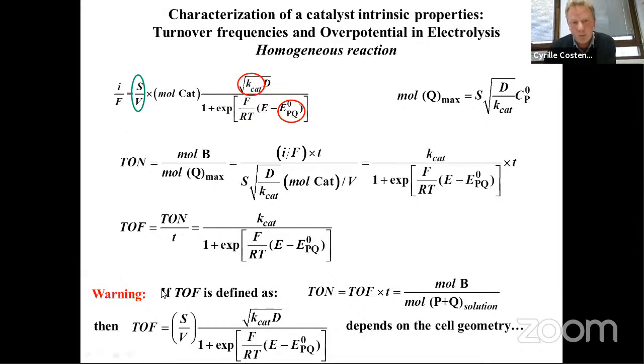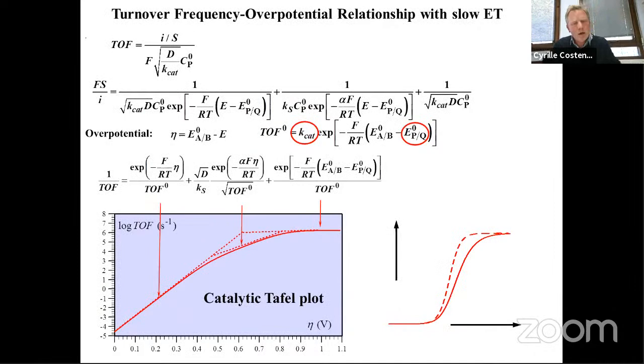And of course, you have to be careful, because if you define the turnover frequency without taking into account only the catalyst in the diffusion reaction layer, as I just mentioned, your turnover frequency will depend on the cell geometry and will not be characteristic of the catalyst. Okay? So now let's introduce some more complexity. So far, I have assumed that the electron transfer between the catalyst and the electrode surface is efficient and just governed by the Nernst equation.